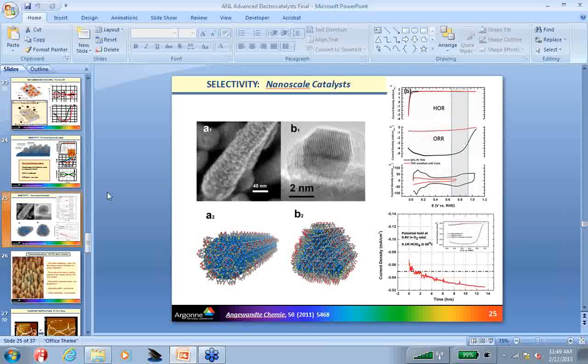Considering corrosion of carbon, I would expect certainly, especially in fuel cells during start-stop conditions, that corrosion of carbon would be substantial. We should keep in mind that platinum is also acting as a catalyst. But if we can completely block the oxygen reduction on the anode side with a very simple method, we expect the cathode would stay below or around 1.05, 1.1 volts. At this potential, I think most likely we are going to have a stable material and hopefully also stable carbon.